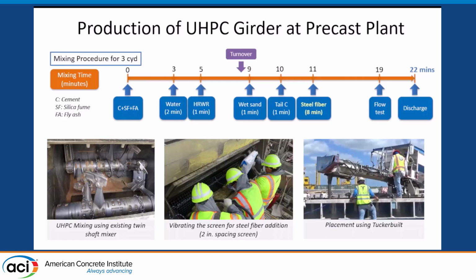And so finally, after about 19 minutes, we conduct a flow test and then double check the workability, that it's not flowing too much where we're worried about fibers settling, and that it's not too stiff, that it's going to be difficult to place. And then this is going to be discharged into a Tucker-built truck at the plant where they convey it or bring it back to the beds where the precast girders are being cast.